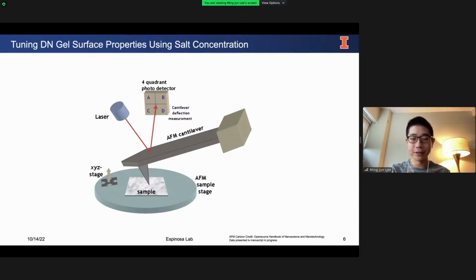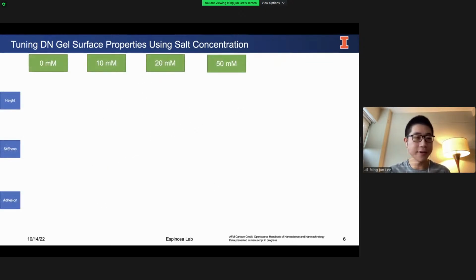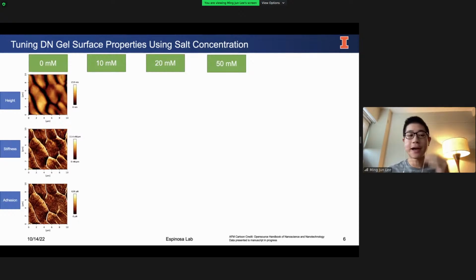Next, I would like to start talking about surface characterization, the adhesion and friction properties. And to begin, I'd like to show you this diagram of AFM, or atomic force microscopy. The way this works is that there is a small cantilever with a very sharp tip that touches the hydrogel, and then a laser from above shines onto this cantilever and reflects into a sensor, a photodetector. As this cantilever travels along the hydrogel surface, the laser spot keeps moving, and that gives us our signal. In the following slides, I'll be showing you quantitative imaging, or QI images. This is a special mode from JPK that allows me to extract three data channels simultaneously: the height, stiffness, and adhesion of my hydrogel surfaces.